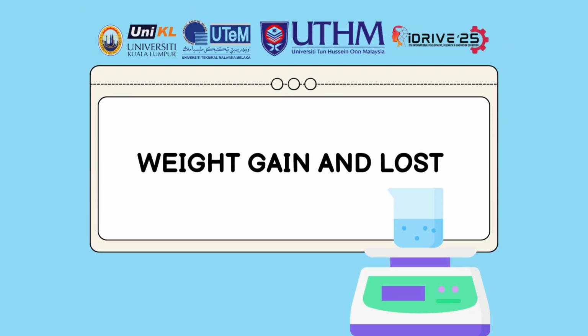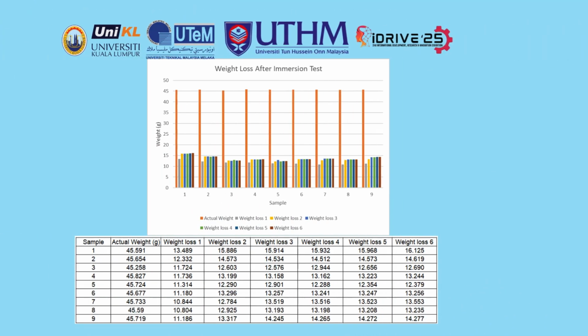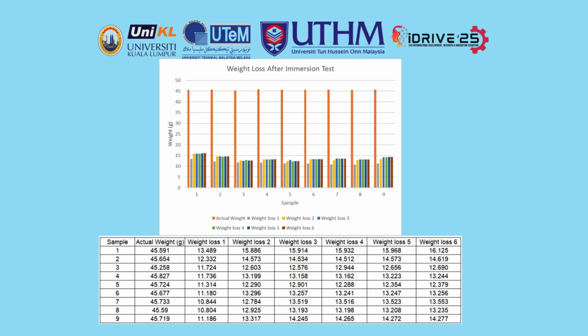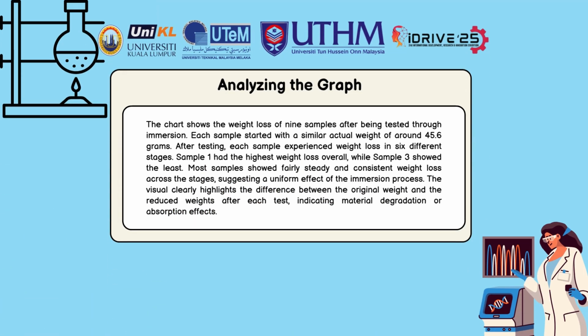Weight gain and loss. The chart shows the weight loss of 9 samples after being tested through immersion. Each sample started with a similar actual weight of around 45.6 grams. After testing, each sample experienced weight loss in 6 different stages. Sample 1 had the highest weight loss overall, while sample 3 showed the least.